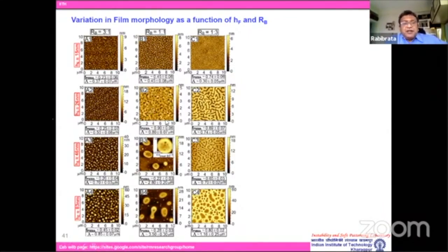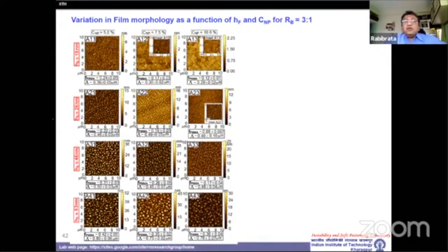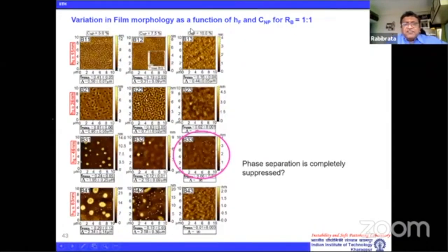So for example, up to 26 nanometers you had a PMMA continuous domain, and at 46 nanometers you have a PS continuous domain. And don't forget that you are actually using a silicon wafer, which always gets covered with PMMA because of the polar bonding, the carbonyl group that's present in PMMA. So now what we decided to look into is how the morphology gets altered if you add nanoparticles. You see some change in morphology, very symmetric, systematic data. I will not go into the detail, but some results are very, very exciting.